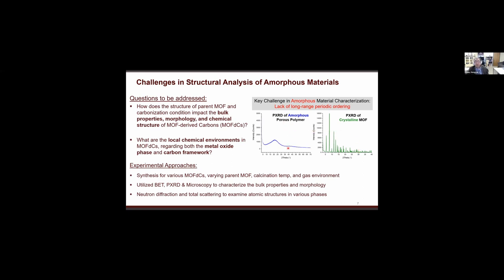So as you can tell, this is a PXRD pattern for a porous polymer, right? On the right-hand side is the crystalline MOF. So for the crystalline one, we have so many peaks, right? So it's easy to do a least squares kind of fit, and then overall you can refine the structure, right? But on the other hand, we only see a couple of humps over here, right? You can't really use Fourier transformation to determine the structure, or use least squares refinement to refine the structure, right? Just not enough data.